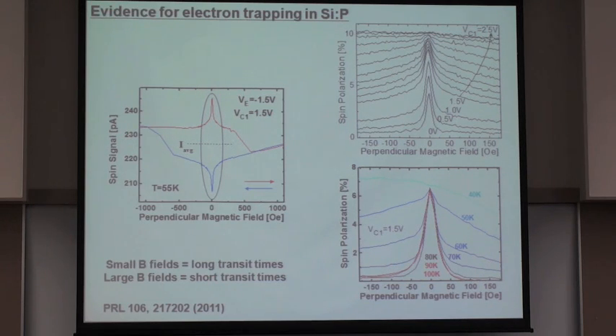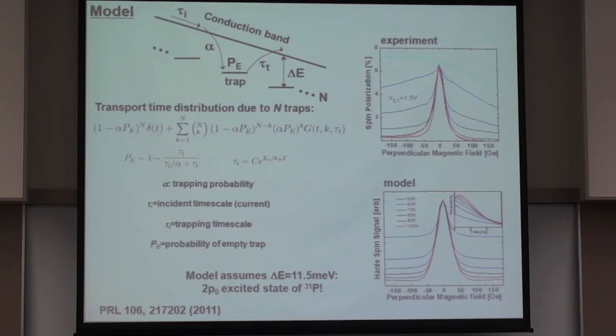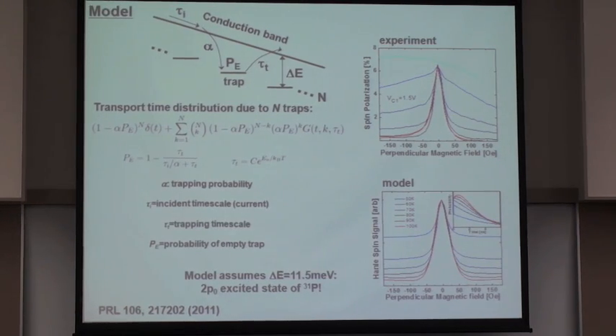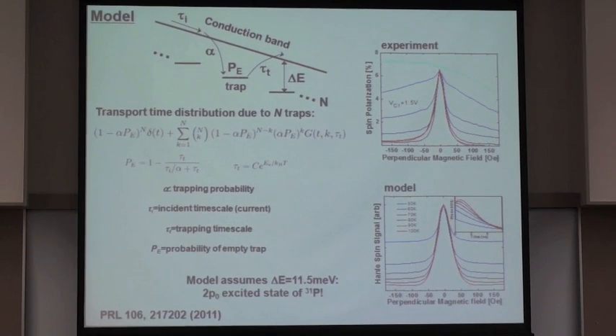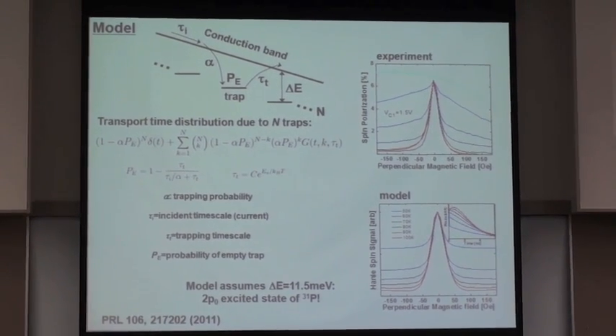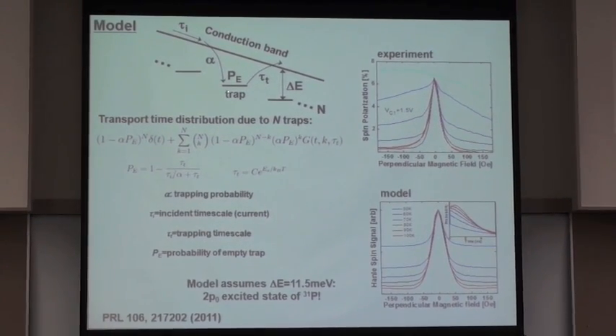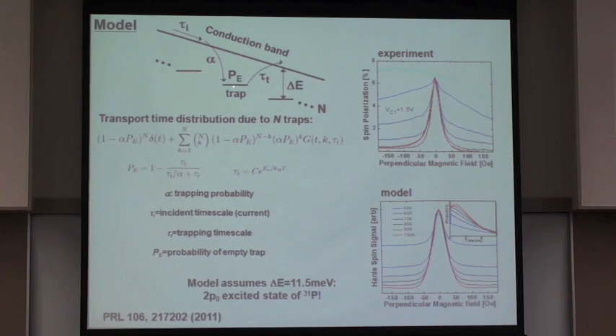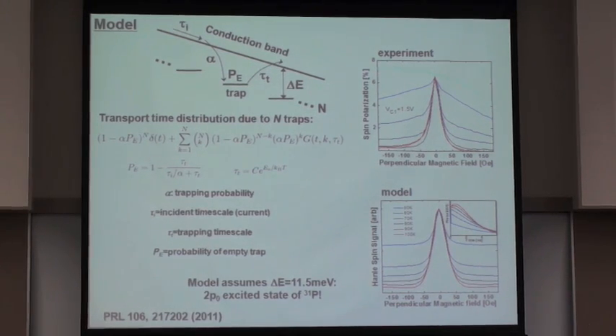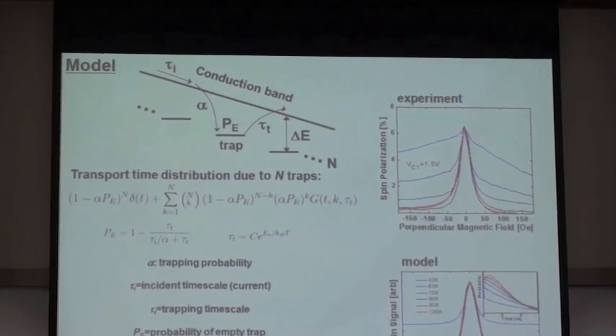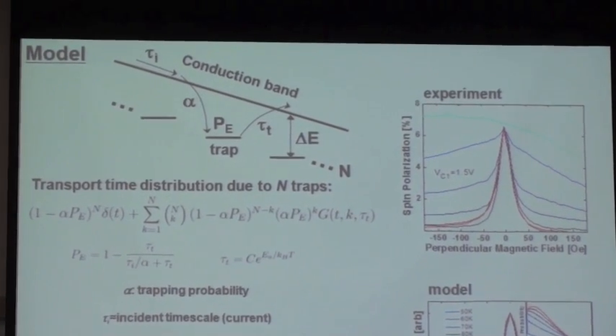So what's this due to? Well, our interpretation of this result, due to the presence of these impurity states, is that electrons are being injected and traveling through the conduction band, but every now and then these electrons are being trapped. They're being trapped in these states just below the conduction band edge, and they're staying there for some amount of time before they're thermally excited back out into the conduction band.